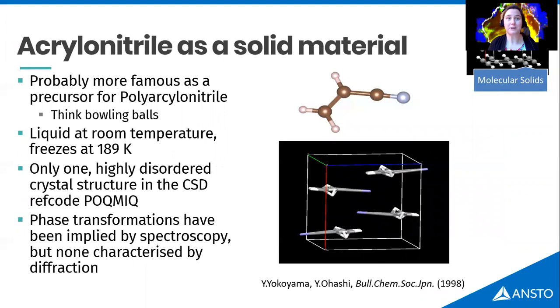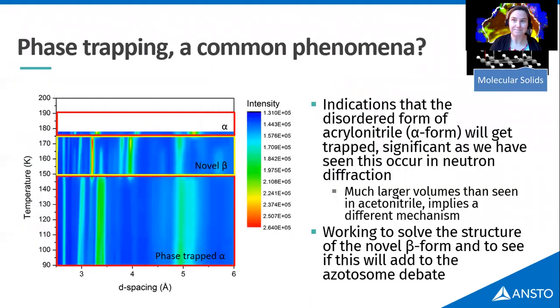And I said I would talk a little bit about acrylonitrile because it's the hot topic in, at least, molecular solids for Titan. It's that material that, if you pick up bowling balls, is polyacrylonitrile, so it's the starting material of that. And there is a known crystal structure, but it is quite highly disordered. It's sat there on a mirror plane and so flipping across all the time. There's been some phase transitions implied by spectroscopy, but none characterized by diffraction.